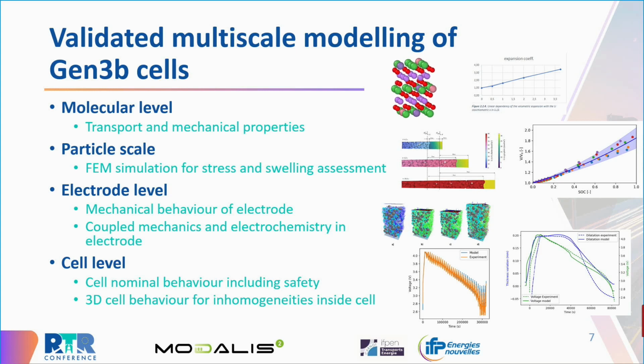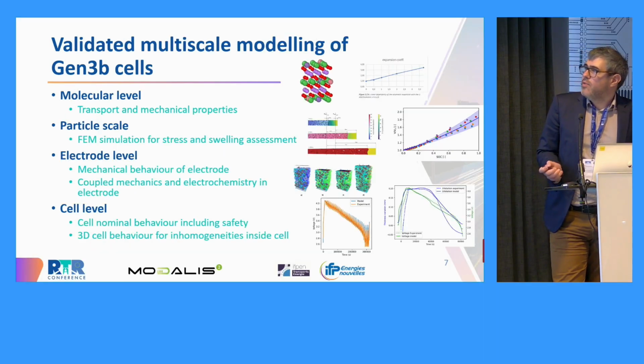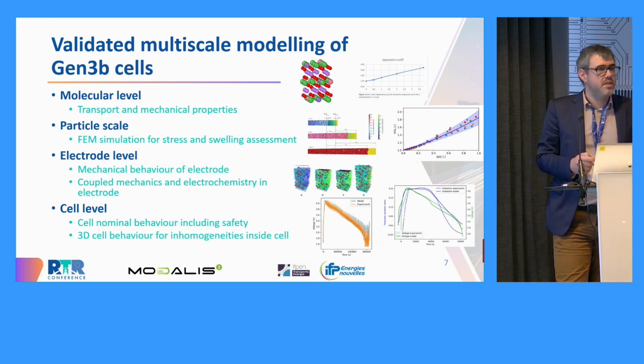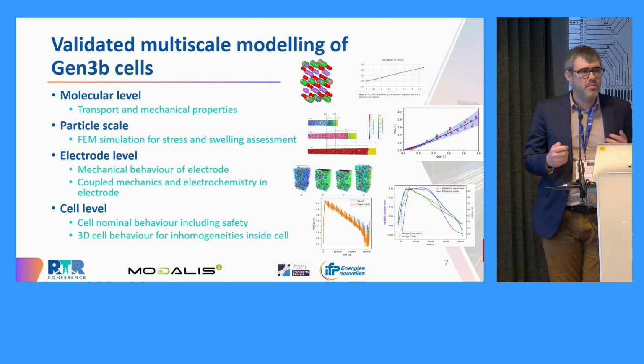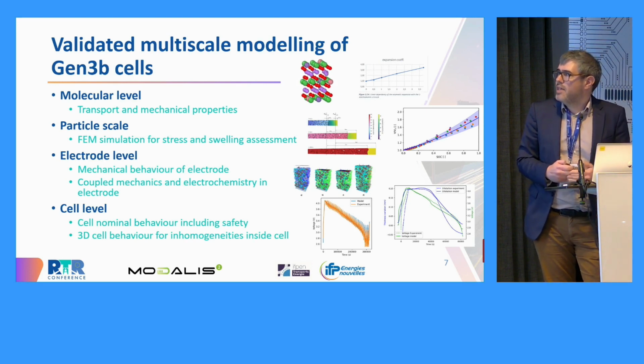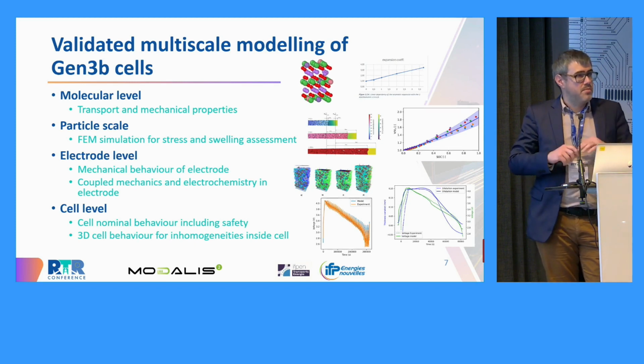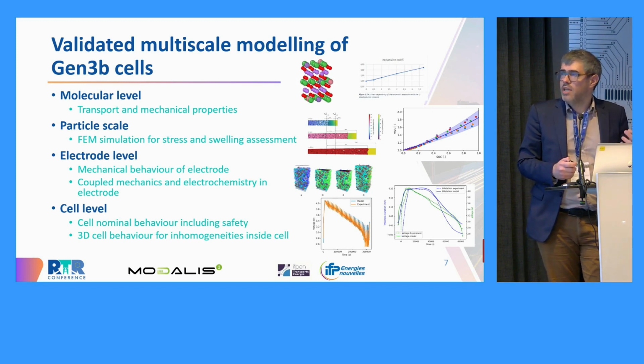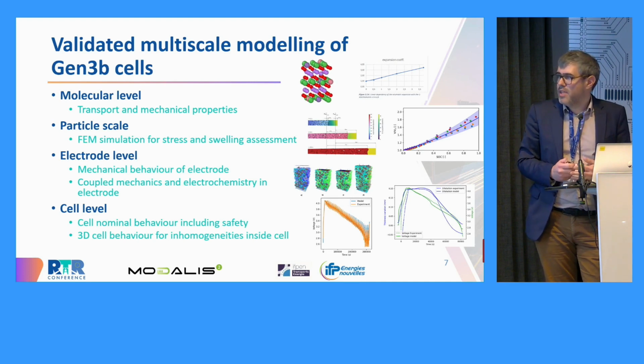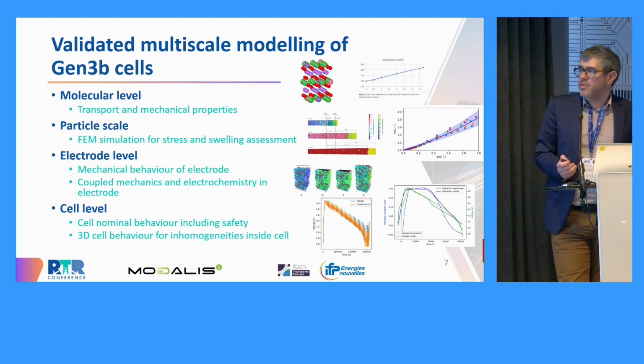So from the molecular level, we developed some specific models in order to understand the transport behavior and mechanical behavior of the materials. These parameters were then used in a particle scale model, which is here, where we could understand how the particles made of silicon and graphite would swell because of intercalation and alloying. This gave us some specific behavior of the particles that could be implemented into an electrode level model, where we could understand how the electrode will behave during the cycling. And this was integrated into nominal behavior, including safety, for the full cell and 3D cell behavior in order to understand the heterogeneity effect on the battery behavior.